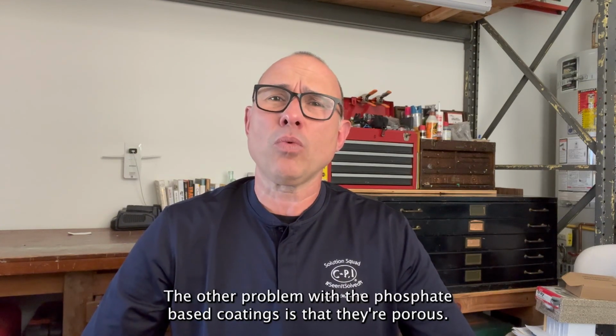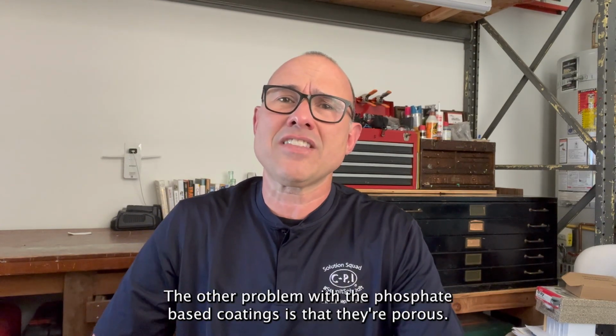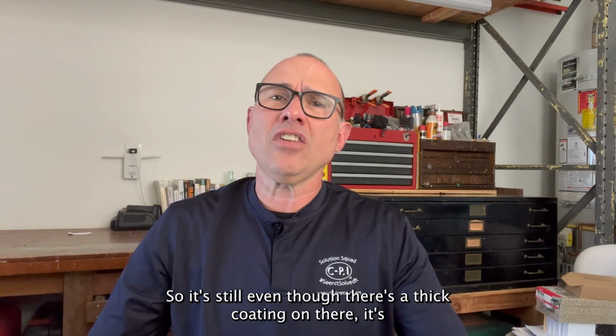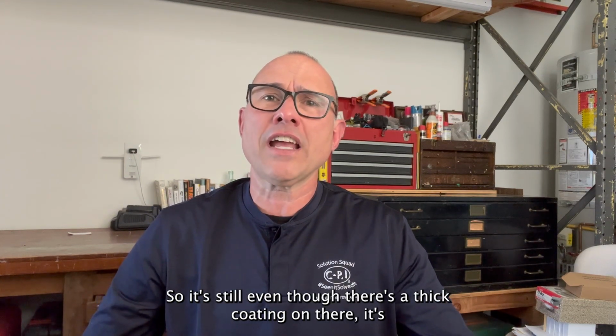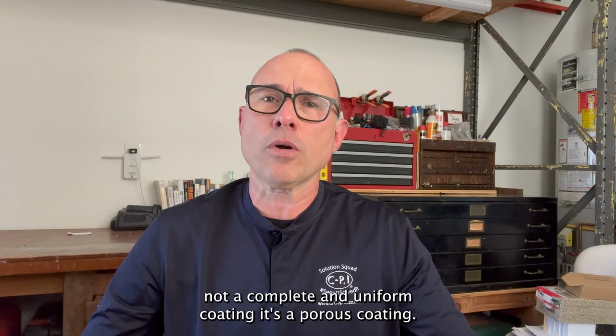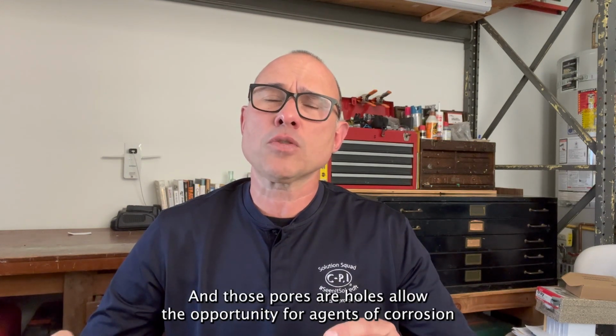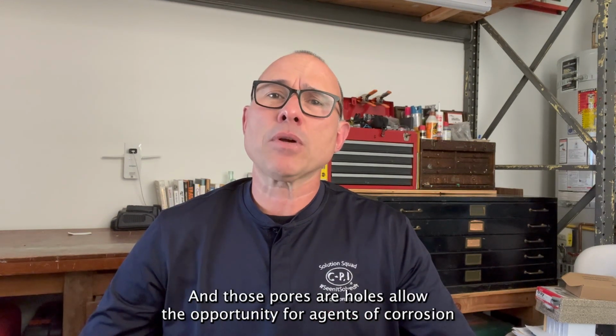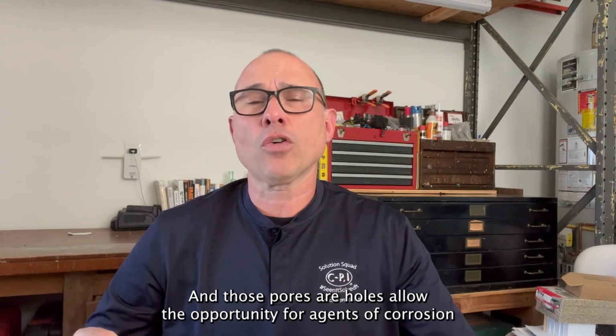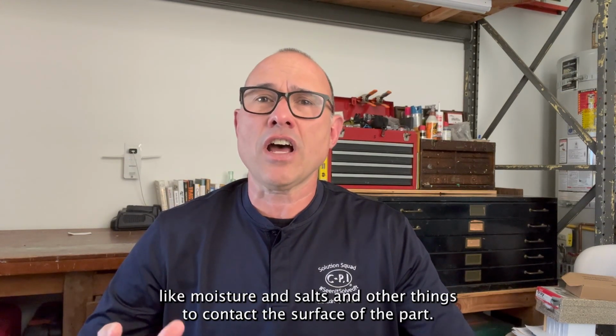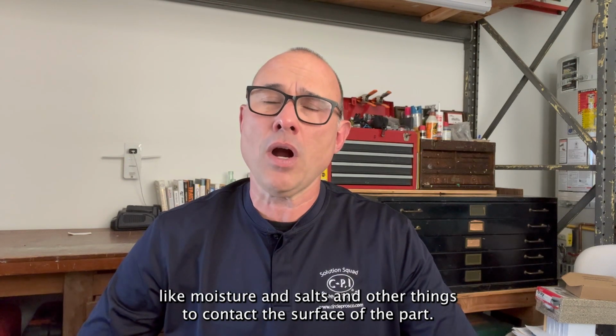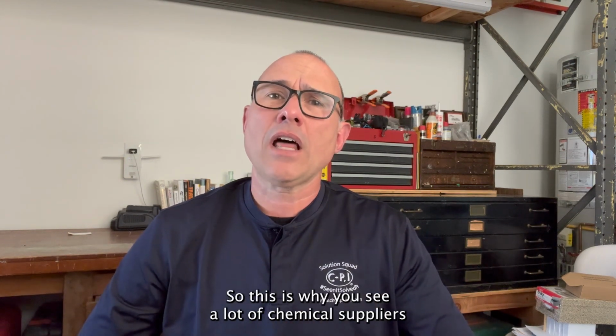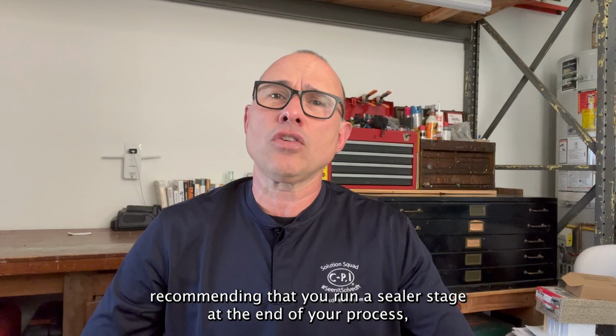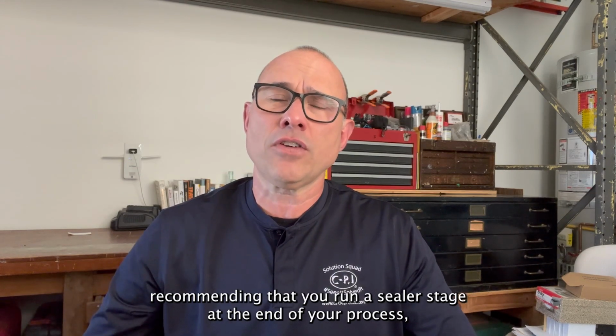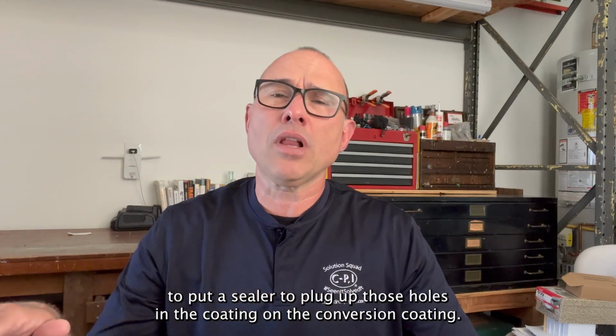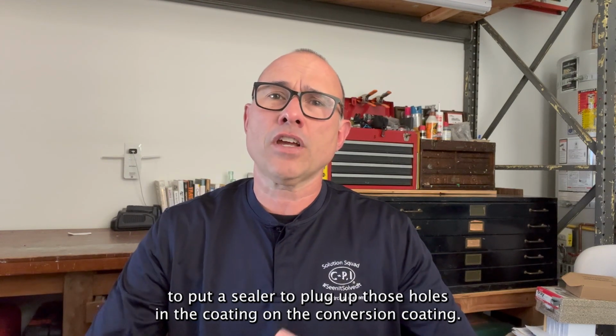The other problem with the phosphate-based coatings is that they're porous. So even though there's a thick coating on there, it's not a complete and uniform coating. It's a porous coating, and those pores or holes allow the opportunity for agents of corrosion like moisture and salts and other things to contact the surface of the part. So this is why you see a lot of chemical suppliers recommending that you run a sealer stage at the end of your process to plug up those holes in the conversion coating.